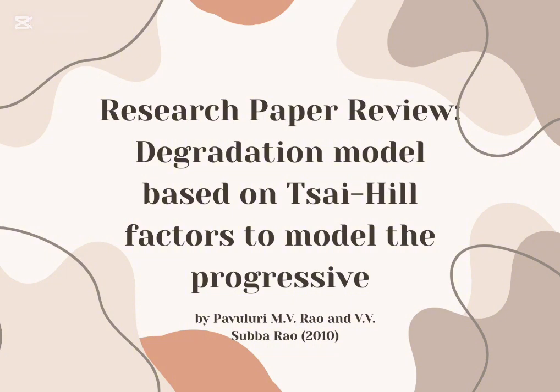When failure was detected in a lamina, its stiffness was reduced according to which Tsai-Hill term, longitudinal, transverse or shear, contributed the most to failure. If the longitudinal term dominated, it represented fiber failure, signaling ultimate failure of the laminate. If the transverse or shear terms dominated, it represented matrix cracking or fiber matrix debonding. If multiple terms contributed equally, it was treated as total matrix failure, where the layer loses nearly all load carrying capacity. This approach allowed the model to simulate the gradual weakening of the laminate as damage accumulated, a much closer reflection of what happens in real structures.